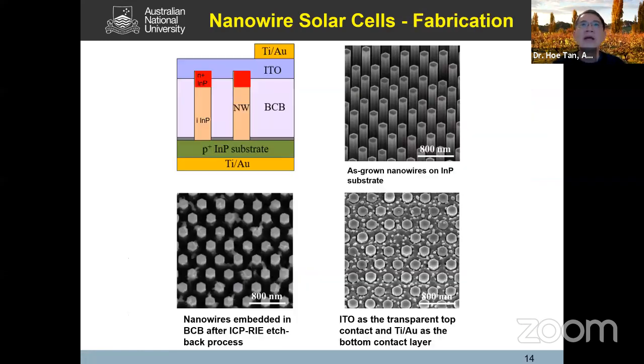So once we've grown our nanowires, as you can see here, we grow indium phosphide nanowire on a P plus substrate. So this is the intrinsic absorption layer. We have an N plus contact layer. So after we've grown this nanowire, what we need to do is we need to make electrical contacts. Okay, but electrical contacts is not so trivial. You know, a lot of semiconductor tools are designed for planar structure. So we need to develop this fabrication process.